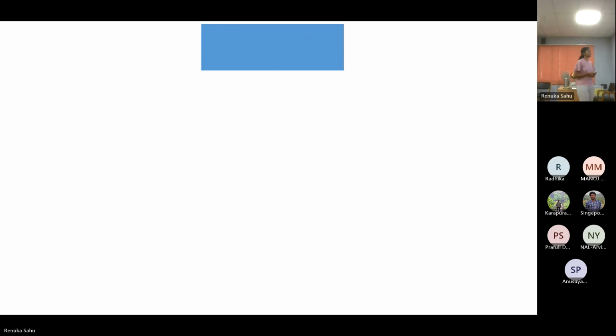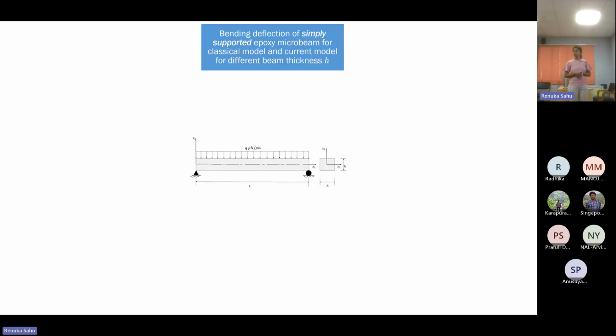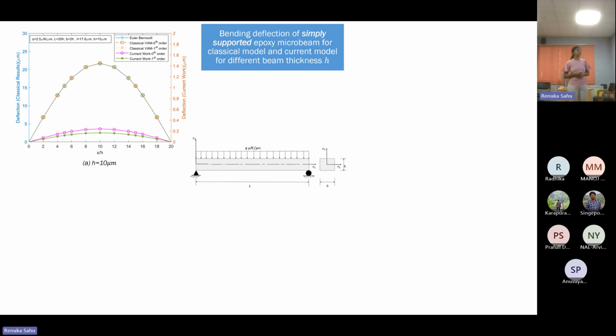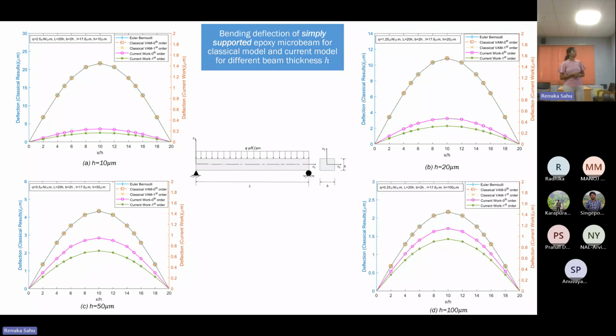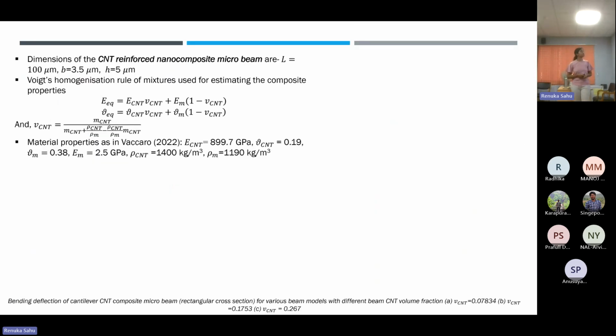We have done the same for a simply supported epoxy microbeam with a uniformly distributed load applied. Again, the same behavior is observed: starting from 10 micrometers thickness there is a huge difference between classical and current work, and as you increase the thickness or size of the structure, the difference keeps on reducing.